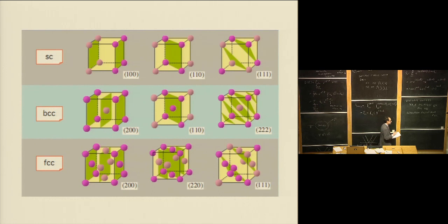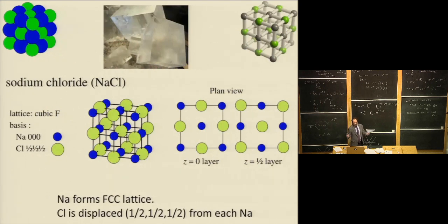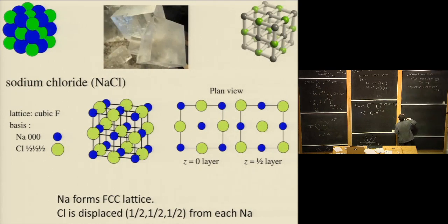All right. One thing that's really cool about these selection rules is that, when you describe any crystal, we can describe a crystal as a lattice, any one of these 14 lattice types, times a basis. This is one of the things we went over when we did crystal structure. For example, sodium chloride, it's an FCC lattice, but then times a basis, which tells you there's a sodium at 0, 0, 0, and a chlorine at 1/2, 1/2, 1/2. The selection rules remain the same independent of the basis. Selection rules are independent of basis.